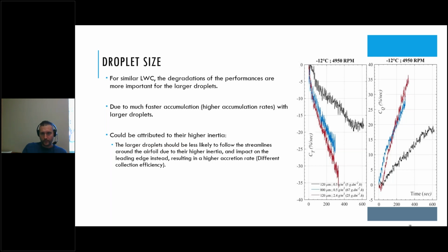Just for example, the red line shows that for the droplet with 120 micron, you need 5 times higher precipitation to reach similar degradation. And this faster degradation is due to the faster ice accumulation on the blade, so a higher accumulation rate with the large droplets, and this could be attributed to their higher inertia. The larger droplets are less likely to follow the streamlines around the airfoil due to their higher inertia, and then impact on the leading edge instead of following the flow around the airfoil during rotation, like the smaller droplets will have a tendency to do. So it's basically caused by a different collection efficiency of the blade.